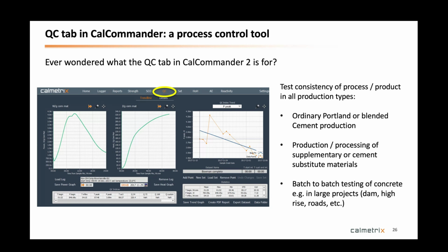And every time I have this curve, I will put it in here. I can look at it. I can look at different parameters, which I will go through. And then I can add it to what we call a data set. It's actually a small database of those curves. And I can look at different parameters, which I will go through in a minute. And I can see how they evolve over time. So I can see a trend line. I can see how things evolve over time, and that tells me a lot about consistency, because trend lines that have a heavy slope and things that go up and down like this are not very consistent.